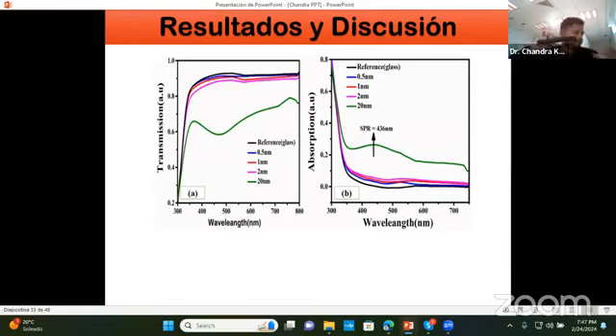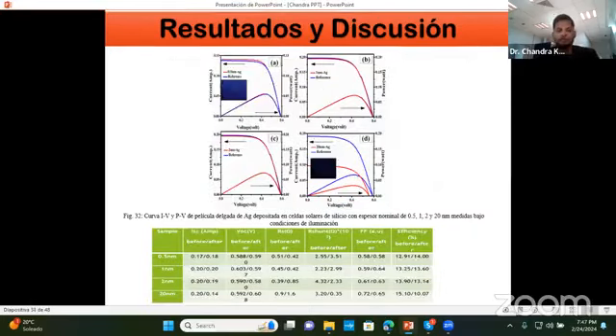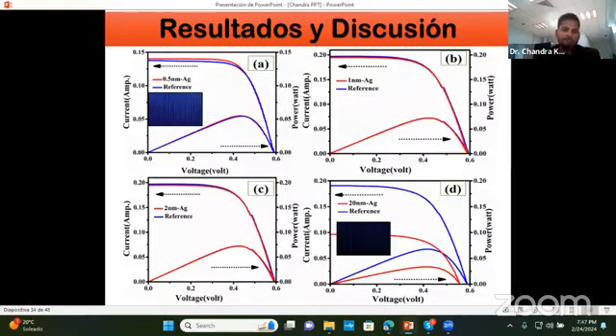If this is silicon and this is silver, then the electron and hole vibrate or oscillate at this interface, and that is called SPR, surface plasmon resonance. So these are the solar efficiency results. See how the color varies. If we coat 0.5 nanometer silver, the color is blue, because this is an ultra thin layer, and silver has a stable capability to trap the light.